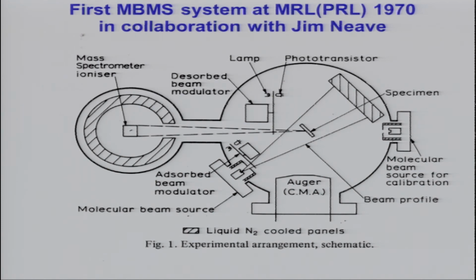So you see in this first system we have the molecular beam source. I'll show you in a moment. It was modulated by an in situ rotating motor, fairly unique. Ferranti made this UHV motor, which you could buy. And that allowed the molecular beam to impinge on the substrate, and the desorbed beam could also be modulated by a second motor. And the mass spectrometer was situated here in a liquid nitrogen cooled region, so that it was a first pass through there, and anything that went through was frozen on there. And we had a second molecular beam source here to just look at what comes from the source itself.